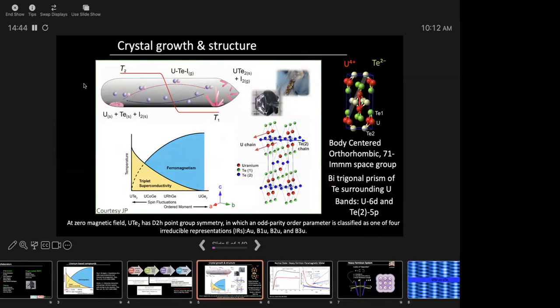And this is sort of a schematic of the method. This is what the single crystals look like. They're big and beautiful. And this is the crystal structure. It's a body-centered orthorhombic Immm space group. It looks complicated, but it's not that bad. These green atoms and these blue atoms are tellurium, and these red atoms are uranium. So one way to visualize this structure is to think of these trigonal prisms of tellurium surrounding two chains of uranium atoms. So it's a very stripy, chainy kind of material.